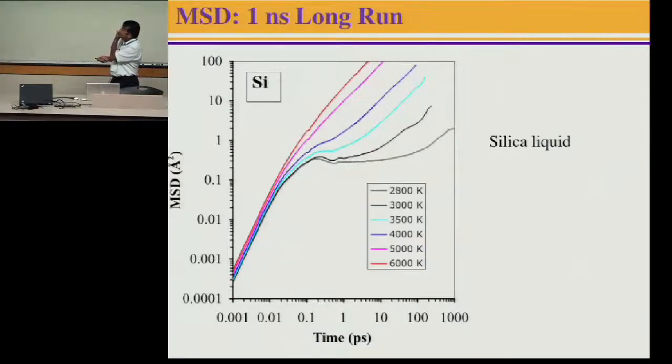Okay, so this is for the previous one, for hydrous silica. The dynamics is relatively fast, but this is pure silica dynamics, very, very slow. I have already completed 1 nanosecond. Still, you start to see some linear regime, but since it is towards the end of the simulation, you are still not sure. So even though you used 1 nanosecond, maybe you have to run for 2 nanoseconds so that this region becomes converged. And only then can you use this MSD value to compute the self-diffusion coefficient.